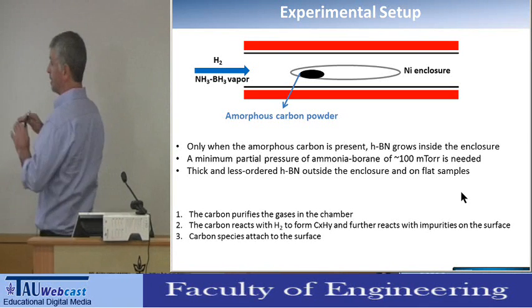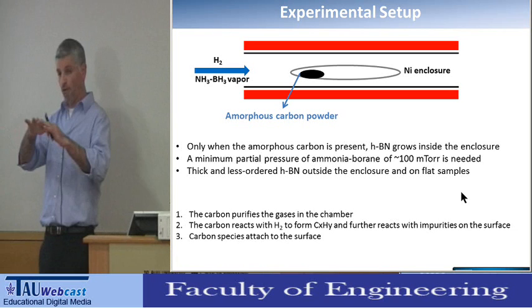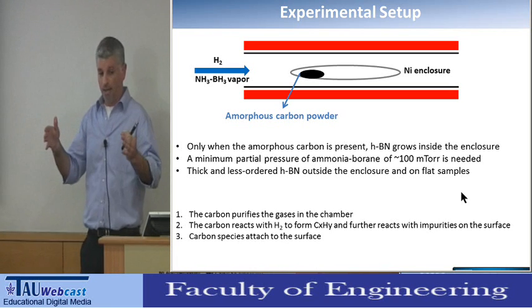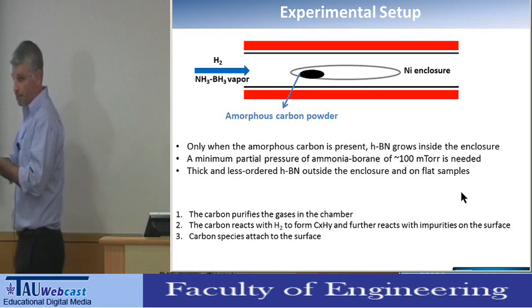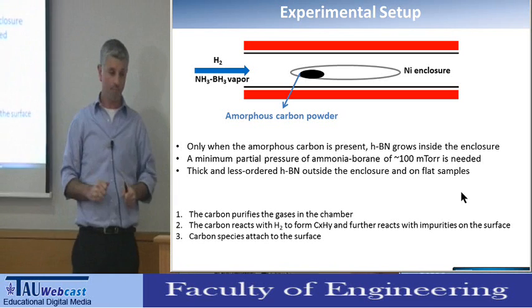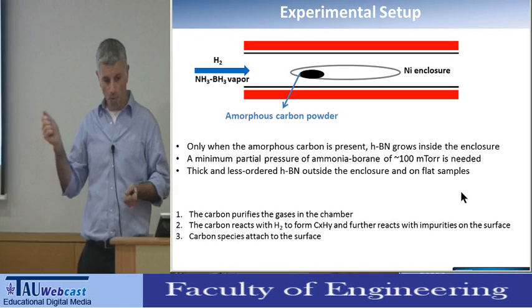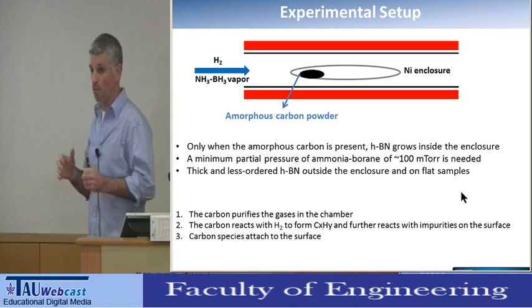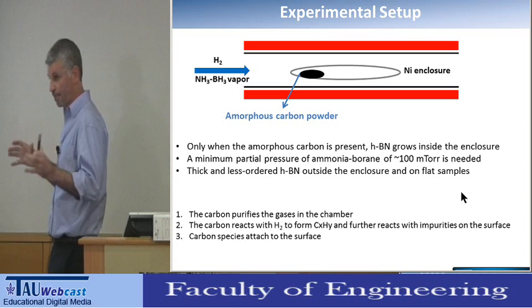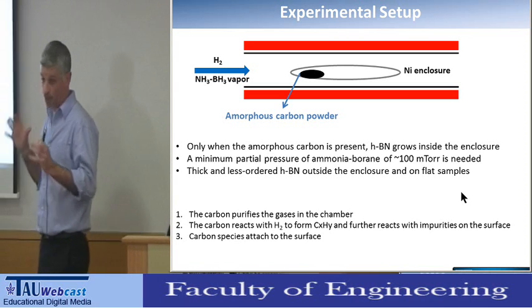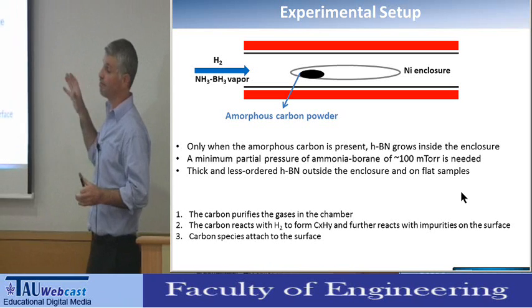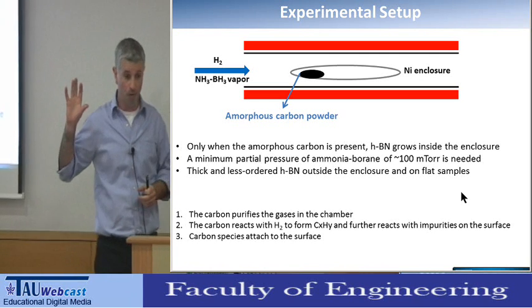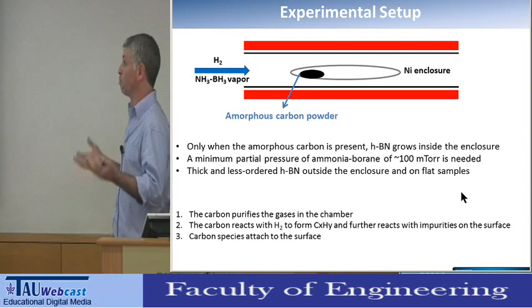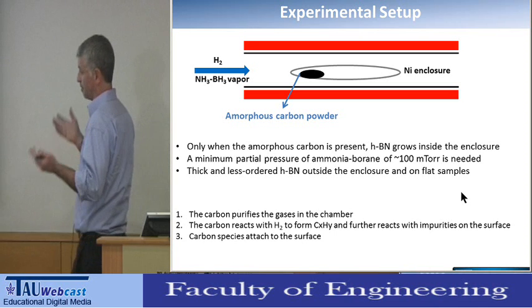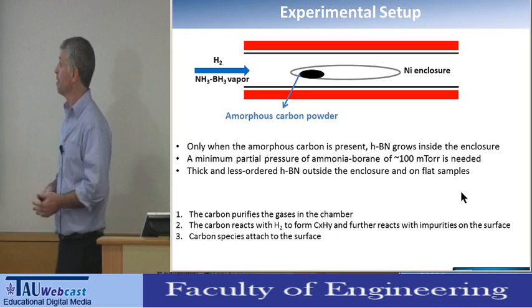In this case, a nickel pocket, which is a nickel foil folded into a closed pocket. This methodology we used for a long time to grow very large graphene domains, and it worked very well for graphene, but it never worked for HBN. We didn't know then why that was.